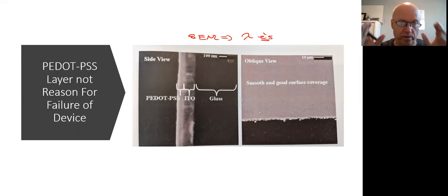I cannot see this with my eyes. I have to use electrons. You see here the scale is 100 nanometers. Here is the glass surface that it's on. Here's the indium tin oxide layer, and here's the PEDOT:PSS layer. On the side view, it looks good, about maybe 50 to 75 nanometers thick. So very thin. And looking at an oblique view, it looks smooth with good surface coverage.